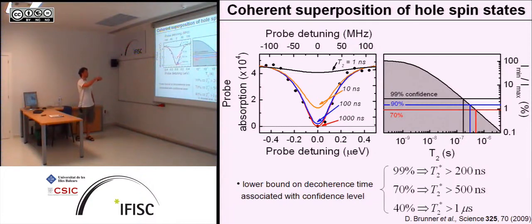But of course this is an experiment, and this is a very beautiful scan. You have more noise and everything. So what we've done is we measured 10 scans, averaged them, and fitted our results to this, and that basically gave us an estimate of the coherence time of this ground state. So what you can see here is a confidence plot showing how confident you can be that the whole spin coherence time will be longer than the lower limit we calculated here.